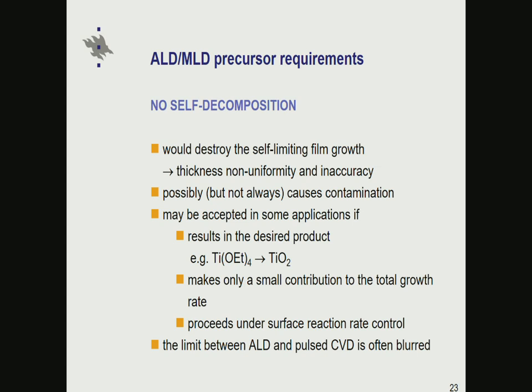Basically this is valid so that the decomposition takes place only on the surface, so it's a surface reaction rate control. So CVD is okay if it's under control, let's put it that way. And in fact, with many precursors that are used in ALD, the limit between a true ALD regime and CVD regime is quite broad. So it depends, for example, on how long precursor pulses you are using, whether the decomposition has time to set in or not. And that's an important thing to keep in mind.